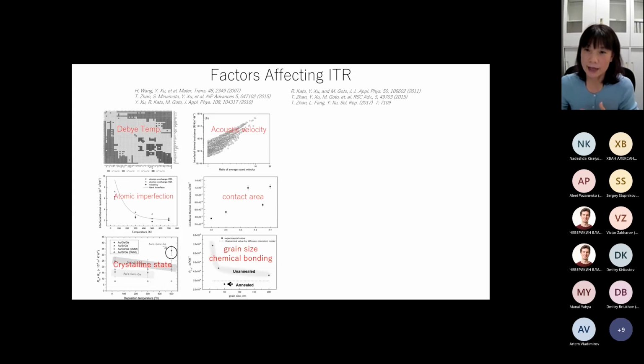And in the past 15 years, we have studied the factors affecting ITR by experiment, physical models, and molecular dynamic simulation. And we find the ITR is a very complicated phenomenon. Of course, the properties of the materials, like the Debye temperature and acoustic velocity, will affect it seriously. And also the mismatch between these properties of the two materials will have a great effect on it. Besides that, it is also affected by atomic imperfection, like vacancy and atomic mix exchange at the interface.